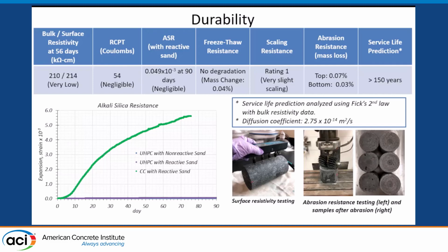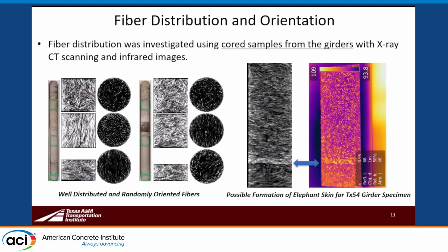This plot is just showing the expansion strain versus days for several mixes that were compared. The one that you see in green is a conventional concrete with reactive sand, and then these flat lines are showing the expansion of UHPC with both non-reactive sand as well as a reactive sand. Because of very little water availability, we are not seeing any ASR issues in this mix based on our lab testing.